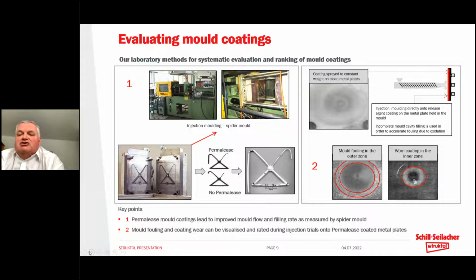And of course, one of the first things that a good mold coating should do is provide a greater flow property, so to reduce the surface friction and allow a more extensive flow to occur. And so typically we would expect to see a greater degree of mold flow, as can be depicted by the 2 black spiders that we can see there. One with Permalease, our mold coating system, and below with a lesser degree of mold filling, mold flow, without a